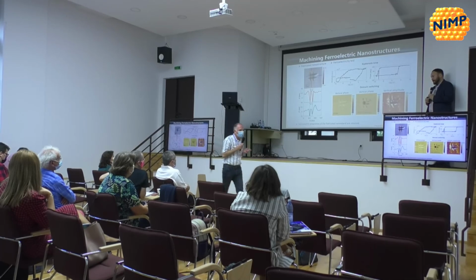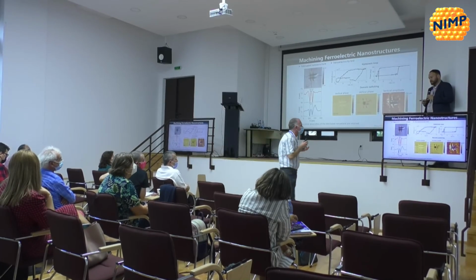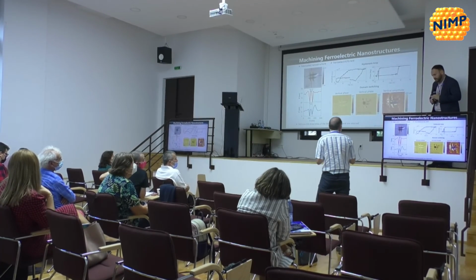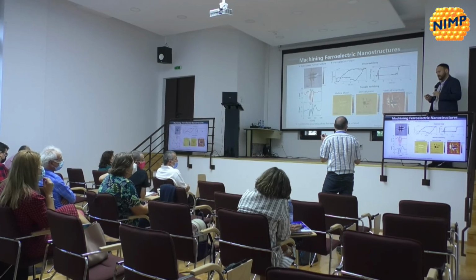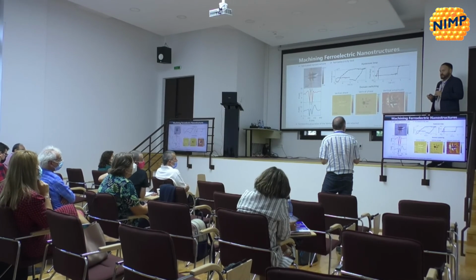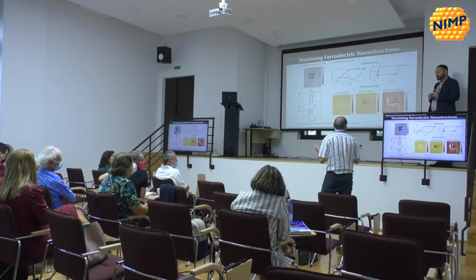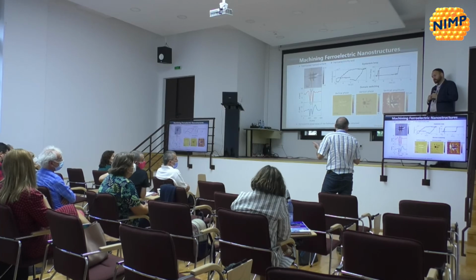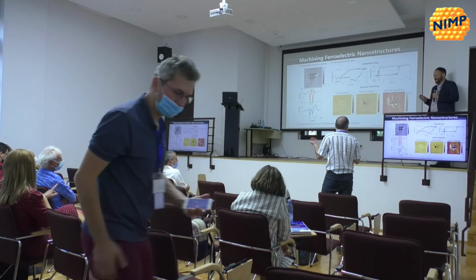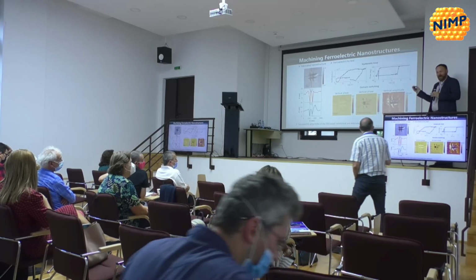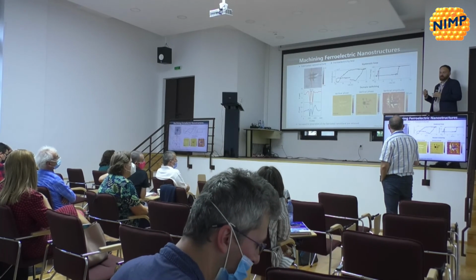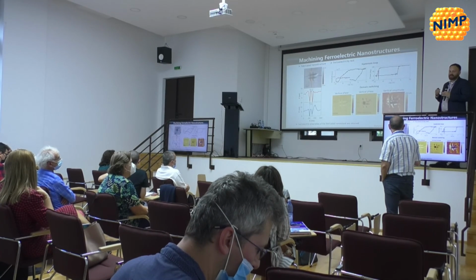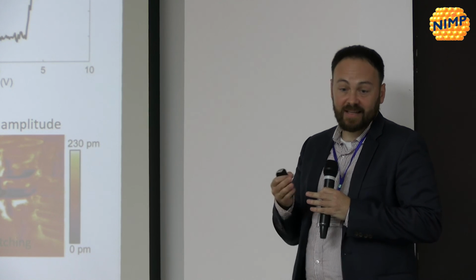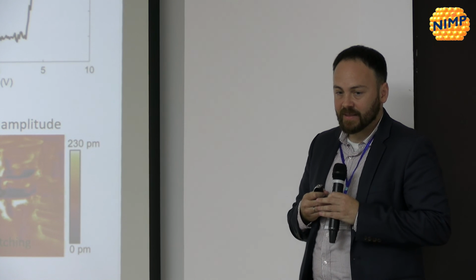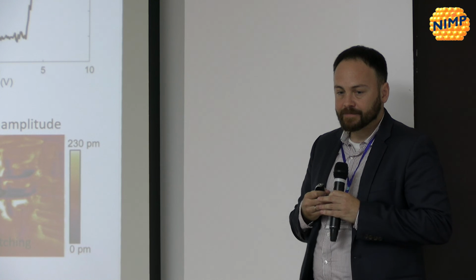Thanks. Yeah, I may be too late, but I also have a remark about this dead layer. So what is this dead layer? Is it a different, dissimilar material, or is it just the material itself that has no ferroelectricity? Because in the second case, when you apply a force, maybe this material becomes somehow ferroelectric. I can't know for certain. I don't know what happens to the dead layer itself when we apply a force. We treated it as a similar dielectric material that doesn't switch, with the same composition, more or less. Okay, so it's the same material at the end.